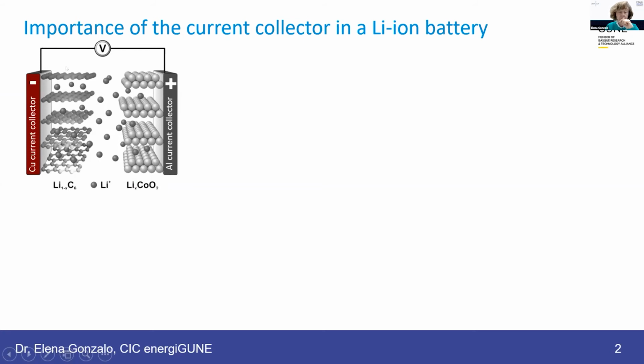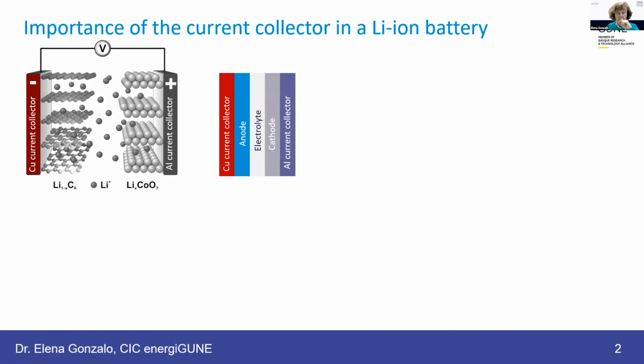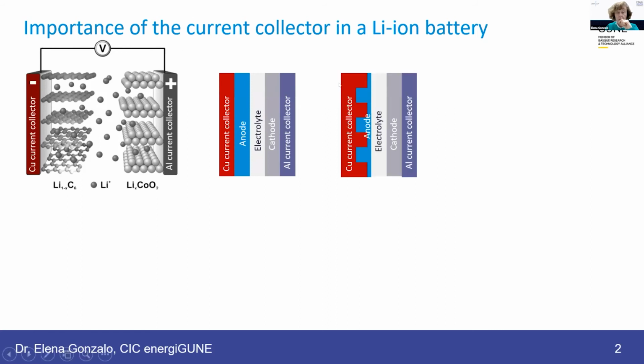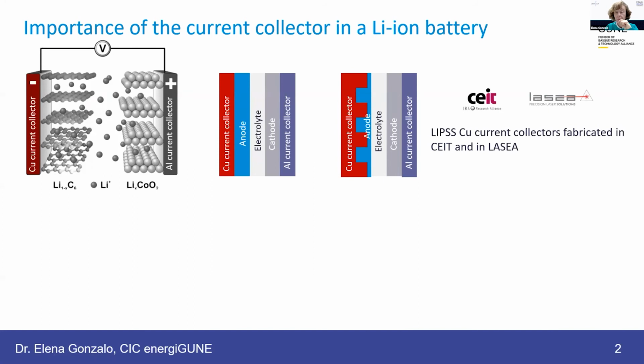In this particular case, we have graphite as anode material and lithium cobalt oxide as cathode material. And in between those, we have the electrolyte. This is a scheme of what is inside a cell, and you can see here what LIPSS have done in our current collectors. Our partners have done the structure modification in order to get some different characteristics of our cells. So these two particular partners that have already spoken, Ceit and Lasea, have fabricated the LIPSS current collectors that you will see today in my presentation.